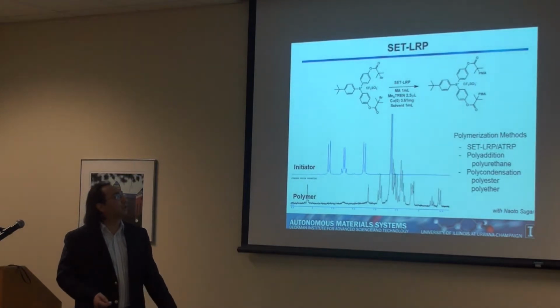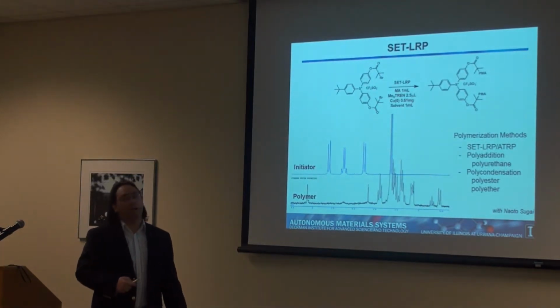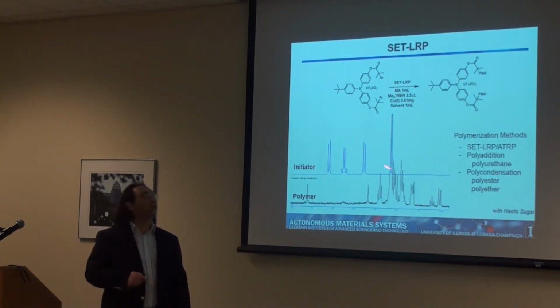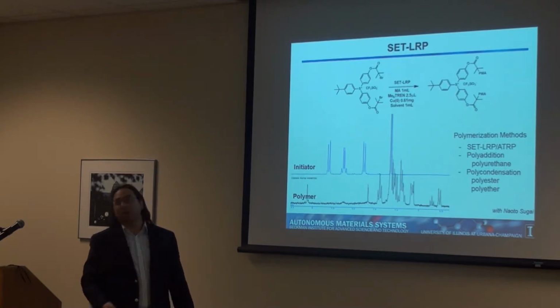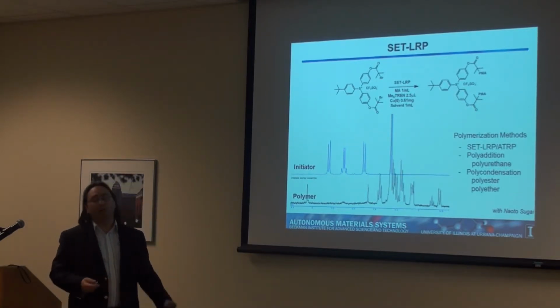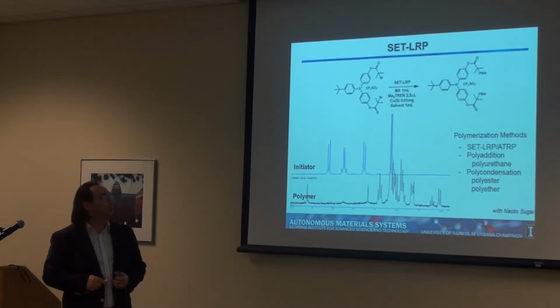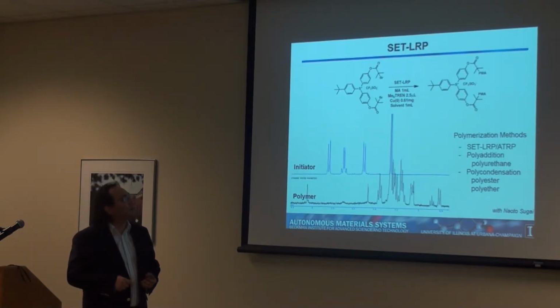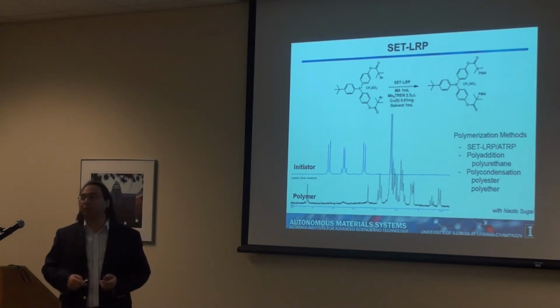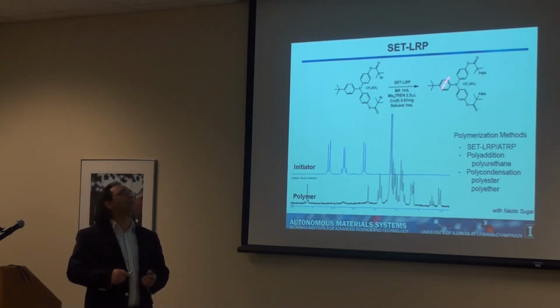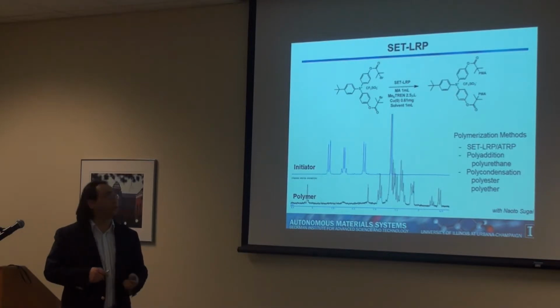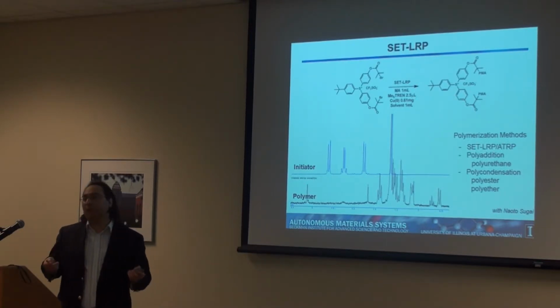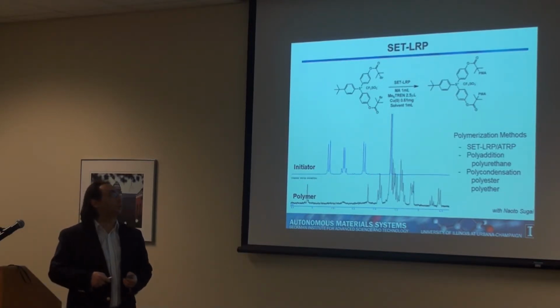So we just take this molecule, we add again methyl acrylate as the monomer, and make this polymerization using a copper catalyst. And we got a very good polymer. The problem was that when we looked at the NMR, we found out that this structure had already decomposed during the polymerization. So it seems that this sulfonium salt is not stable towards copper. It's stable to high temperature, but it's not stable towards copper.